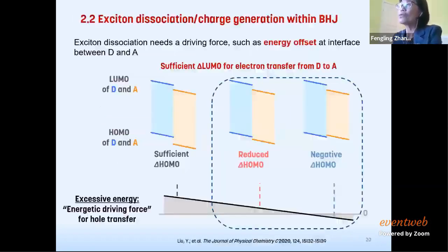So the second part I will show is exciton dissociation and charge generation within the bulk heterojunction. For the charge generation, before, I only talked about donor and acceptor, thinking about how they are spatially mixed. Actually, there is another issue that will influence the charge generation, that's energy offset. Because different materials have different capability to catch the electron. Therefore, this energy offset is a driving force for the exciton dissociation. That's the reason why the bulk heterojunction works better than a pure single material device, because in a single material device, they don't have the driving force for charge dissociation.